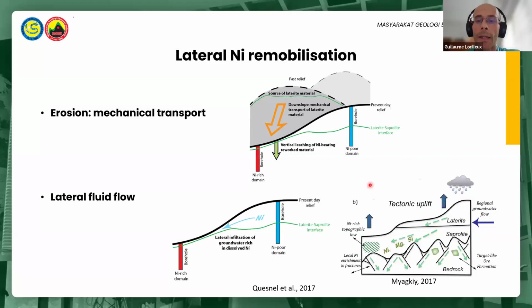Another author, Quesnel, 2017, shows that areas richest in nickel are under thin or no laterite or limonite cover at Koniambo. I should say limonite, I'm sorry, this is coming from the French, actually. Based on the nickel mass balance calculations, two complementary processes are invoked. The first consists of the successive lateral transport of reworked laterite material. So it's a mechanical transport, including nickel-bearing material from topographic high to downslope areas. Leaching of this reworked material could increase nickel grades in the underlying saprolite zone.